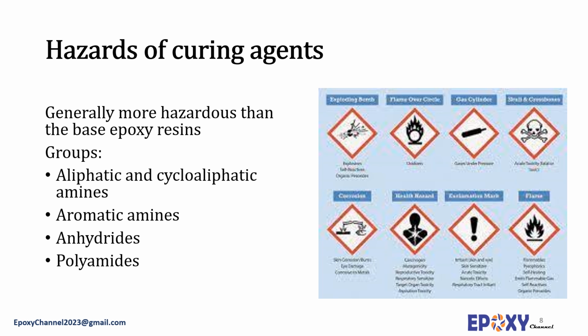Curing agents are generally more hazardous than the base epoxy resins, and specific information on these materials should be requested from the manufacturer. The aliphatic and cycloaliphatic amines, as well as anhydride curing agents, may be skin sensitizers and cause irritation or damage to the skin, eyes, and lungs. Aliphatic amines are strong irritants and potent sensitizers. They are alkaline caustic materials which can cause severe tissue damage, and even in dilute solution form, they can still cause severe eye damage by splashing.